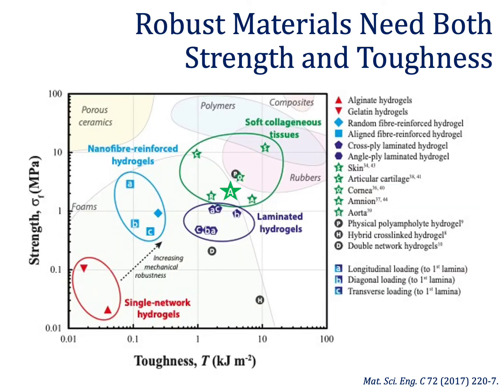And importantly, if we compare these composites that we've made, they're much closer to the properties of the native soft collagenous tissues, including amnion, which is shown on there with a couple different green stars with the letter A in it, reflecting a couple of different studies. We've gotten slightly different values of the strength and toughness on average in the past couple of studies that we've done. But in either event, what's really important about this plot is that the single network hydrogels have nowhere near the mechanical properties of this natural fibrillar amnion tissue, whereas the composites that we make with fibrils in them do start to have mechanical properties that are comparable in both strength and toughness to the native soft collagenous tissue, including amnion.